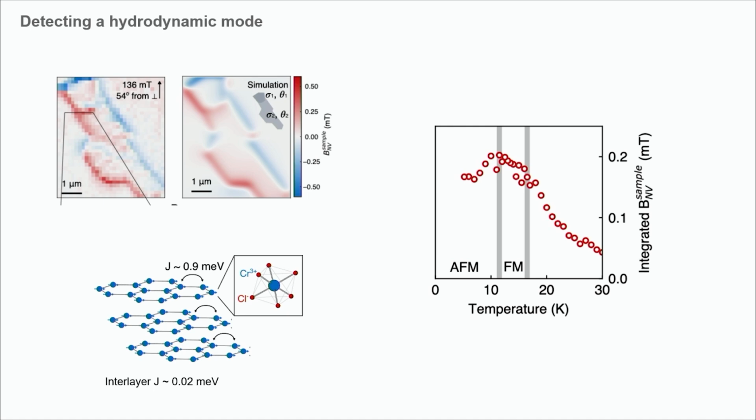Generally speaking, the consensus in the literature on this multi-layer stack is that predominantly the spin dynamics are confined within the layers. There's a very slow process of spin movement between layers. At the static level, the magnetization of the material as a function of temperature, this manifests as two transitions. The first is a transition to a state where you have ferromagnetic order within the layers. And then if you cool down further, you get an anti-alignment of the spins between the two layers. That's at the static, zero-frequency limit.